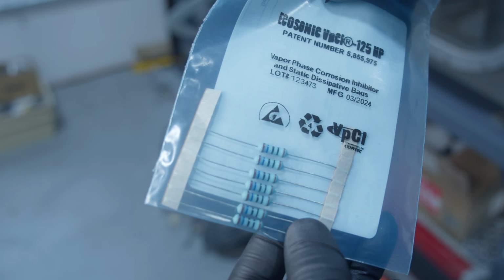Around this time, I was talking to Michael at Applied Ion, and he suggested adding some current limiting resistors. By limiting how much current can jump between the electrodes, we should hopefully control the arcs and prevent that droplet formation. Honestly, I should have thought of this sooner. My power supply has a current limit on it, but I guess it's just not fast enough to tamp down on pulses from arcs. And I don't know, I suck at EE, so this isn't very surprising. So I got some 1 mega ohm high voltage resistors and tried again. The results were not perfect, but encouraging.